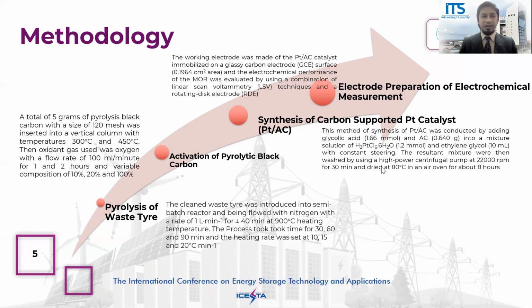The second part is the activation of pyrolytic black carbon. A total of 5 grams of pyrolysis black carbon with a size of 120 mesh was inserted into a vertical column at temperatures of 300 and 450 degrees C. Then oxygen gas, with a flow of 100 milliliters per minute, was flowed for 1 and 2 hours, with variable compositions of 10, 20, and 100%.